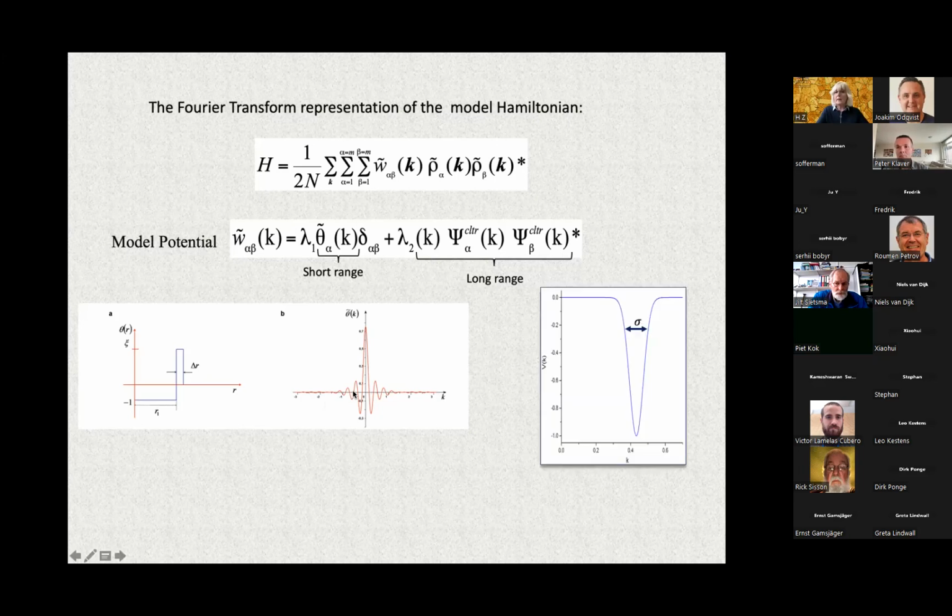And the second interaction, the long-range interaction, means the interaction between the species of the atoms. It was introduced using the structural factor. I will not go into the description; if we have a discussion afterwards, I can explain why it can be linked with diffraction. But just to say that the long-range interaction, which reproduces the crystal structure of a given material which we would like to describe, can be linked with the structural factor for the given symmetry of the crystal.